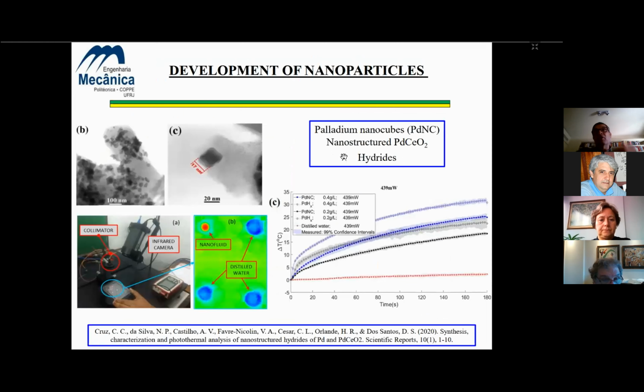Okay, about the development of nanoparticles, in collaboration with our friend Gilson Santos, we recently developed those palladium nanocubes and nanostructured palladium particles, including their hydride form. So we can see here the palladium nanocube with dimensions of about 17 nanometers. And we tested these different nanoparticles in nanofluids also heated by laser.